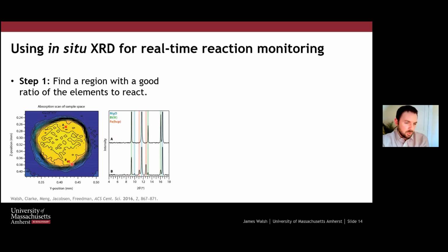As I said, this is kind of an extreme example. You would hope that you don't get regions of, in this case, purely bismuth. We've kind of figured out some of the sample processing since this time, but it illustrates the point that you need to be able to know where you're heating, and that's something that you can do on the beamline quickly. You can very quickly just measure where you want to start your reaction.